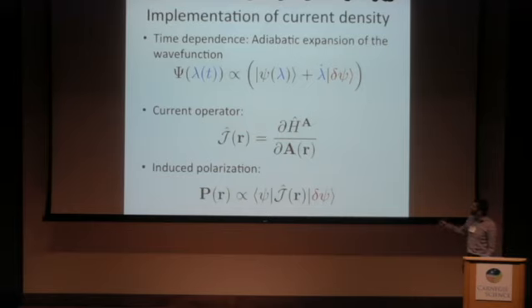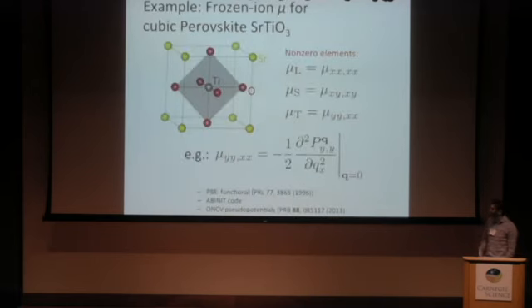So using this adiabatic expansion and our alternative definition of the current operator, we can calculate the induced polarization that we need for the flexoelectric coefficients. So just in the last few minutes, I'll give some simple examples of these calculations. I'll calculate frozen ion coefficients for a very simple material, cubic strontium titanate. For this symmetry, we have three non-zero flexoelectric coefficients, a longitudinal, shear, and transverse coefficient. And again, I'll remind you that we calculate these flexoelectric coefficients by taking the second derivative of the polarization with respect to Q.